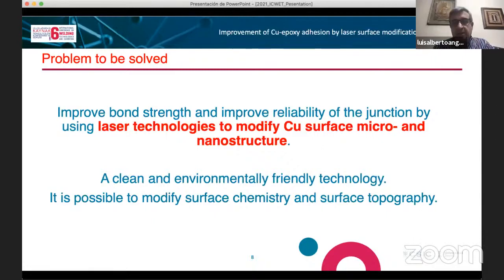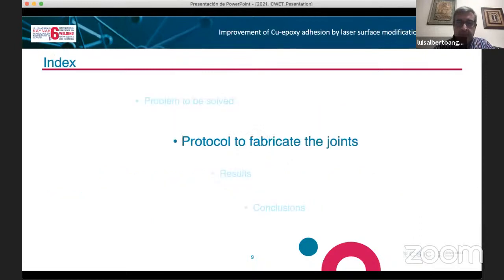Why use laser technologies? Because it's a clean and environmentally friendly technology. We avoid using chemicals in the process. And also because when you modify the surface with the laser, you modify both the chemistry and the surface topography, which are the 2 key points to obtain good joints when we make an epoxy copper joint.